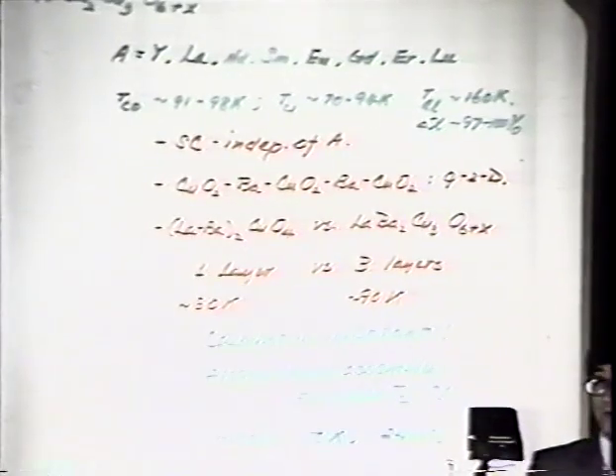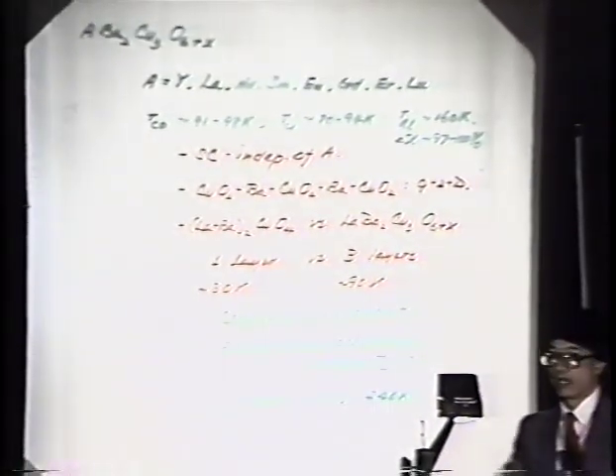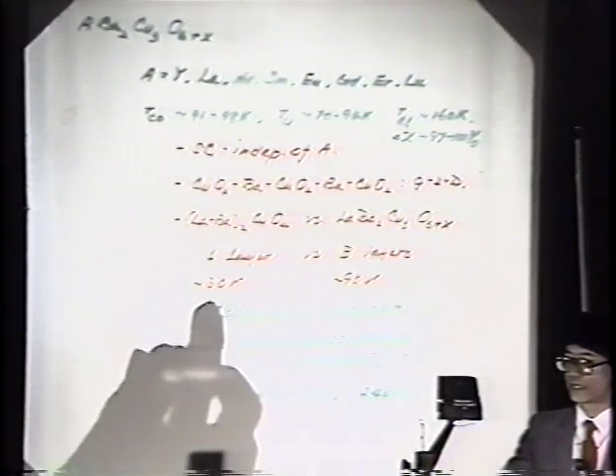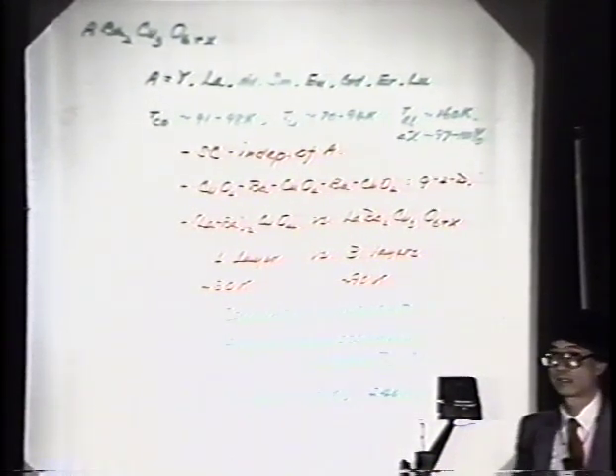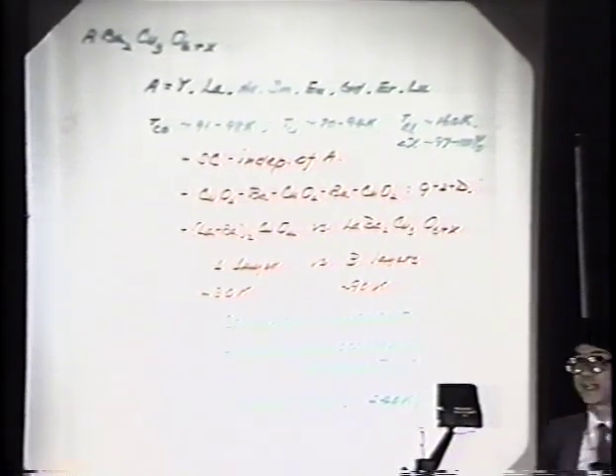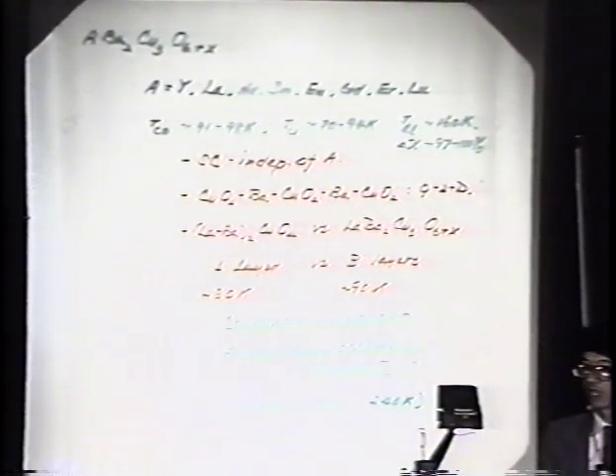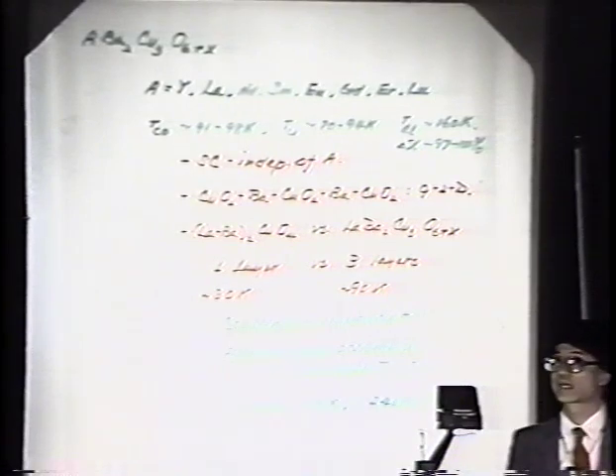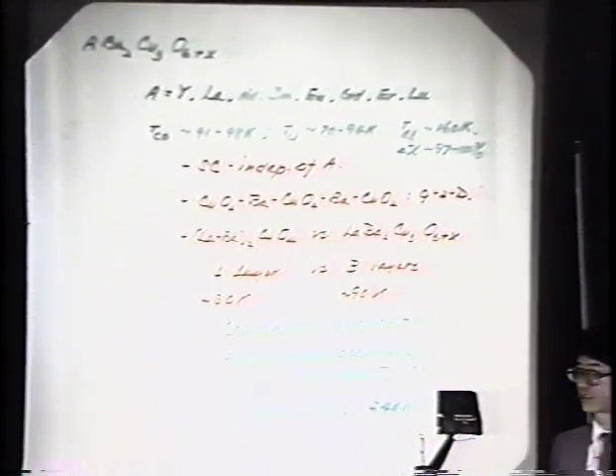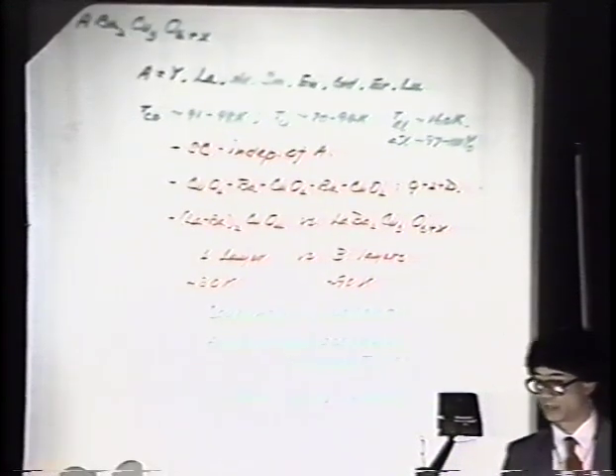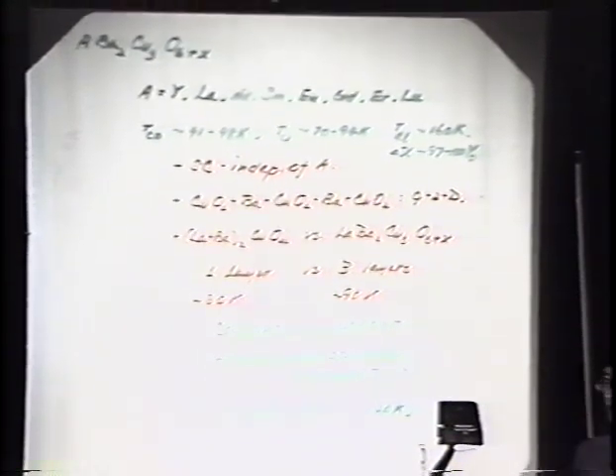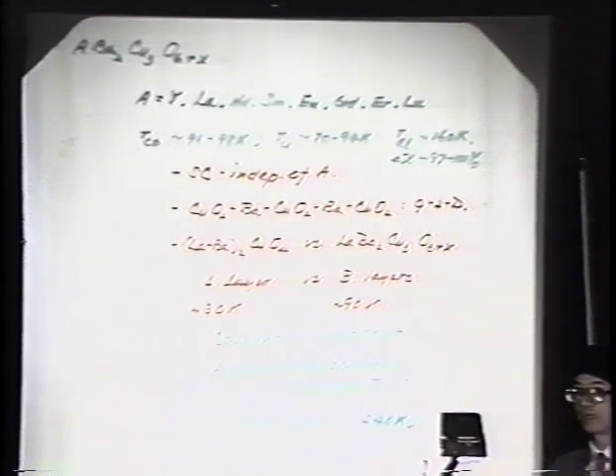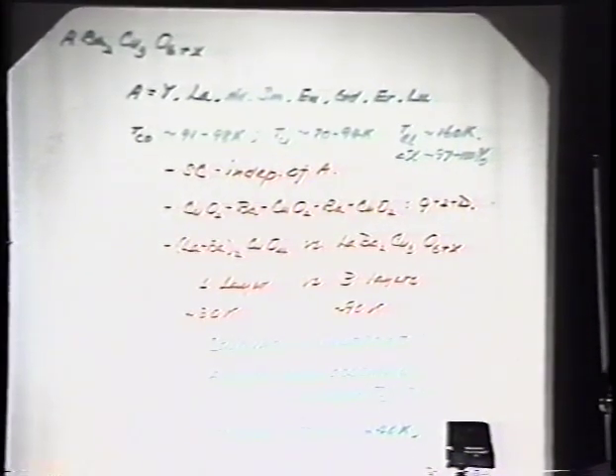And the interesting part is this. If you look into that, in the layer compound, we have 1 layers. They're not coupled. And then in the new compounds, it has 3 layers. One layer has 30 degrees, and 3 layers has 90 degrees approximately. Is this accidental or not? We don't know. But certainly those 3 layers are coupled through the barium. And whether that's true or not, it has to be determined. But based on this result, we think maybe we need bigger layer assembly to get to higher temperature.